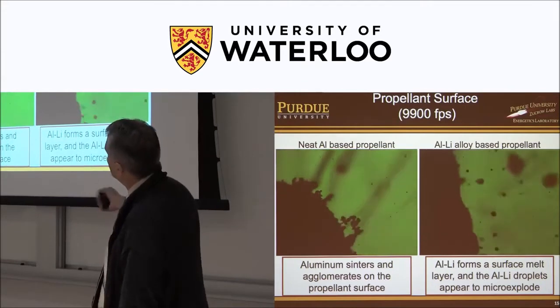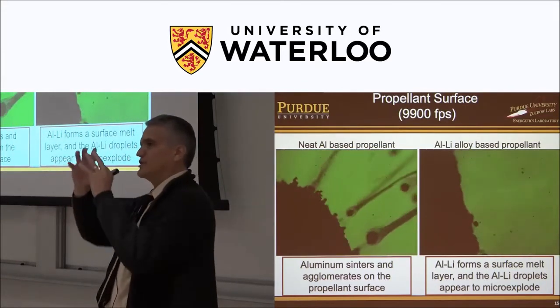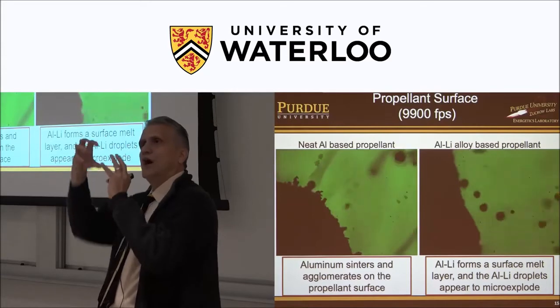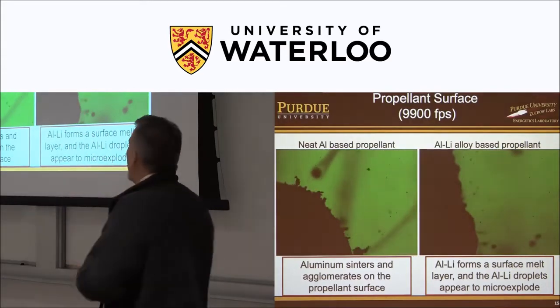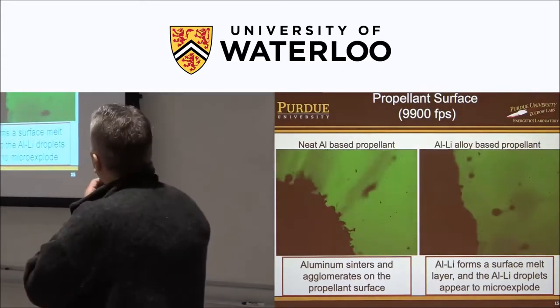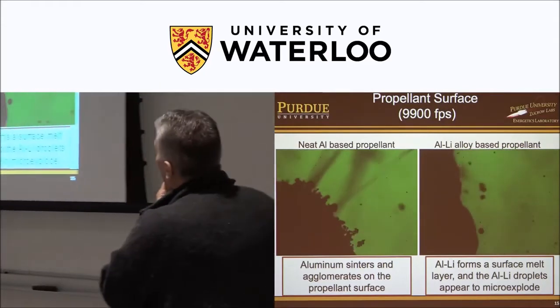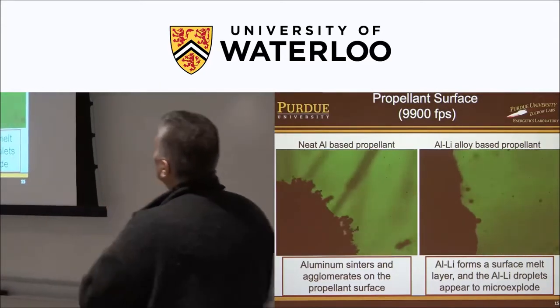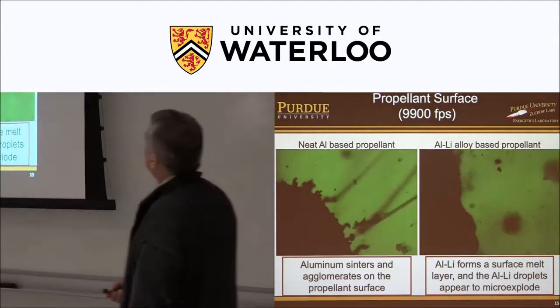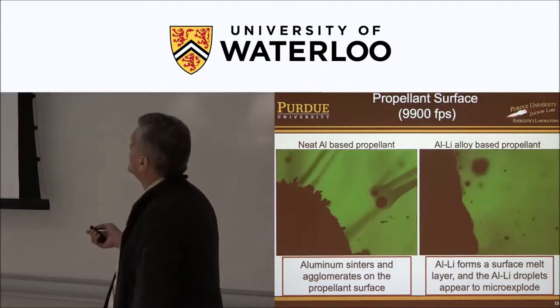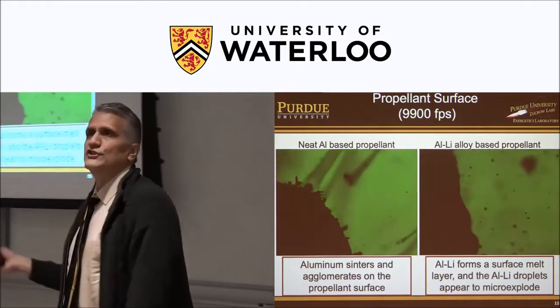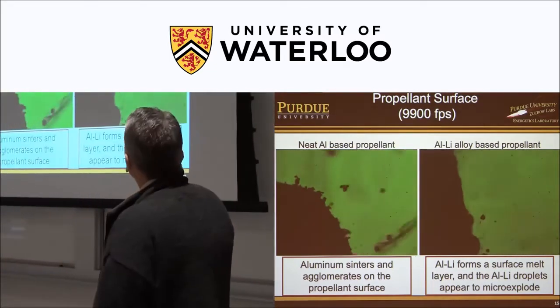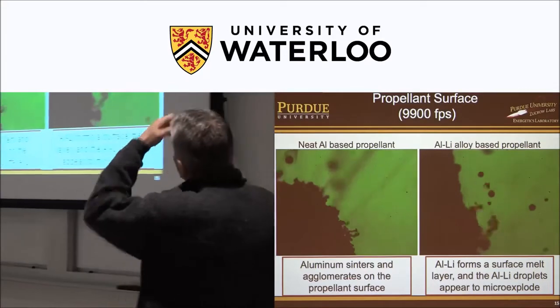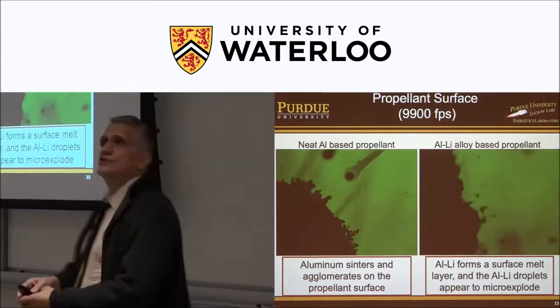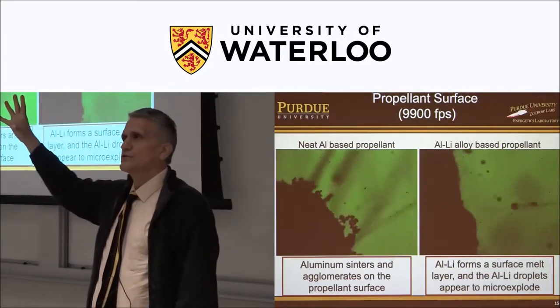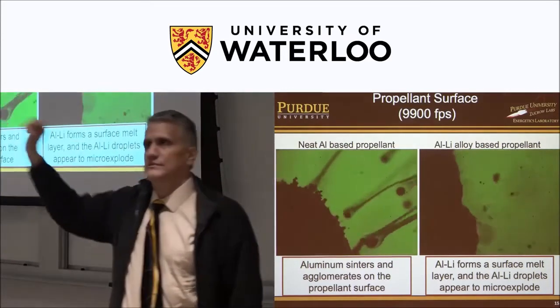If you watch really close, you can see that it's not just a spherical droplet, but there's like this knob. That's an alumina, they call it an oxide cap. But this has been seen before. I think we did a pretty good job imaging it, but this is nothing new. This is typical. If we replace the aluminum with aluminum lithium alloy, the whole surface changes kind of its characteristics. It's kind of bubbling on the surface. It'll throw off droplets. And then you can clearly see these micro explosions. The droplets just self-disintegrate.